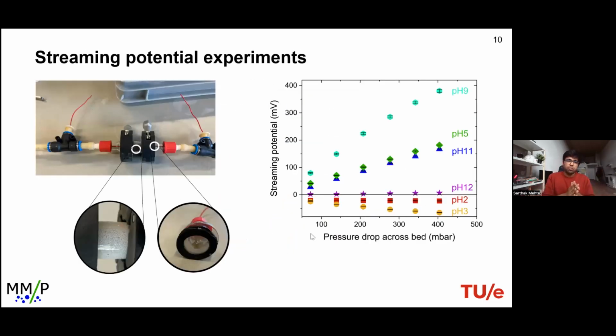So this is what the setup looks like. If you look at the image on the left, we see that the cylinder is filled with silica particles, and we have these SS mesh electrodes that are sandwiched between, containing these silica particles in between. So as we apply pressure, we are able to strip off more ions and we see an increase in potential. This can also be seen in the graph on your right.